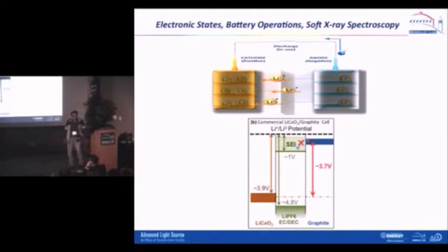However, what happens is on the surface of the anode, there is a very special interface forming. It's called the solid electrolyte interphase, the SEI. And the forming of this SEI is critical. It actually protects the electrolyte from being reduced too much so your whole battery doesn't collapse. So once you form this SEI, your whole battery is stabilized.